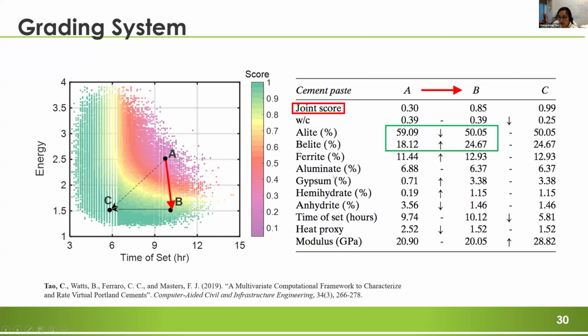For further improvement of the cement, we can reduce the water to cement ratio of cement B to produce cement C, and then the score becomes 0.99 because it decreased the setting time by 40%. So this grading system provides a practical and effective approach to rate the materials according to user requirement for the cement industry.